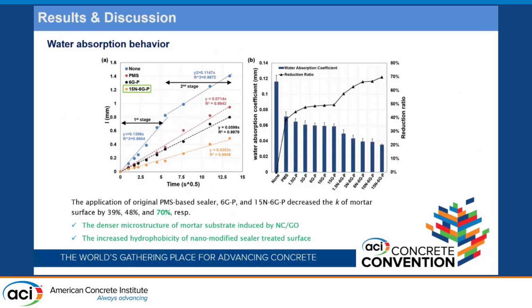Then we test the water absorption behavior. We can learn from these two figures that after adding nanoclay and graphene oxide, the water absorption coefficient will decrease. Compared with the original mortar sample without any sealer, this 15N-6G-P sealer decrease the coefficient by about 70%. This decreased water absorption coefficient could not only be due to the denser microstructure on the surface enabled by these nanomaterials, it's also due to the increased hydrophobicity, as I discussed earlier.